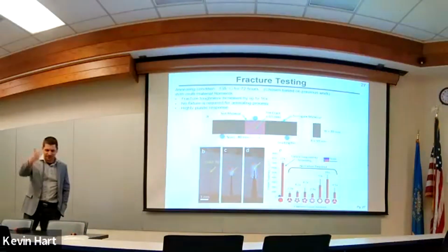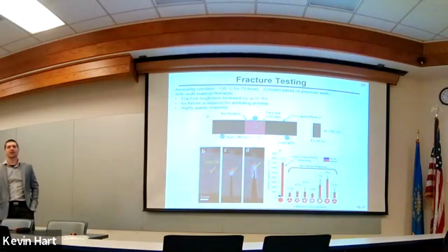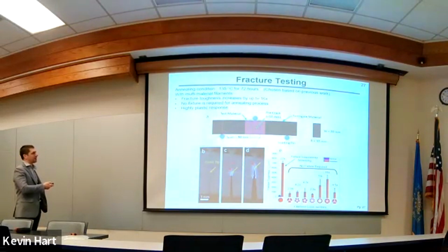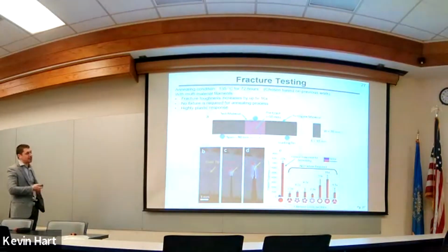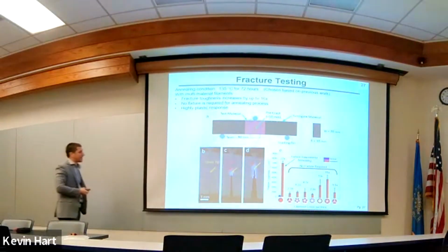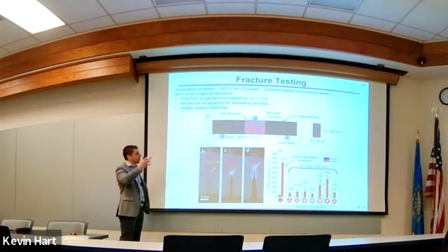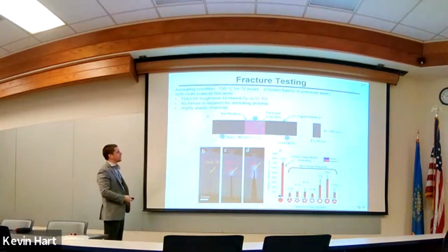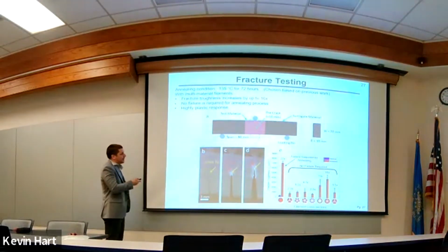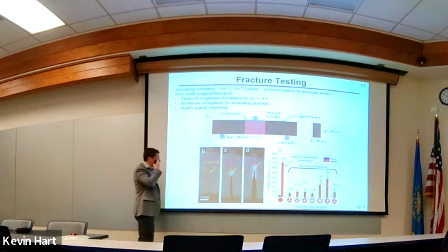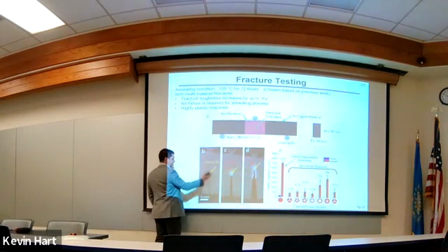So what we did is we went back to our fracture sample. Took our 3D printed filament that we drew down in our draw tower, made all this filament. Now we're going to make a single edge notch bend specimen out of that material, and we're going to evaluate that in fracture. So make this, do the annealing for a certain time and temperature. Here we picked 135 for 72 hours. And that's going to increase the toughness because we have this material here now. Okay? So now we're going to do our fracture test.